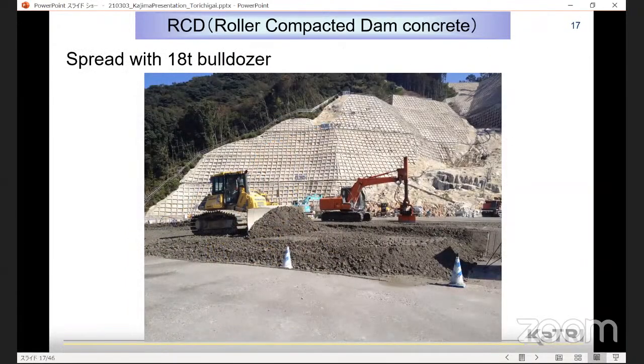The RCD concrete is transported to the construction site. It's spread and leveled by the bulldozer. This photo shows the bulldozer, and this is the RCD concrete. The layer thickness of the spread is determined to be 250 millimeters per layer. By repeating this work 4 times, the RCD concrete will be 1 meter high.